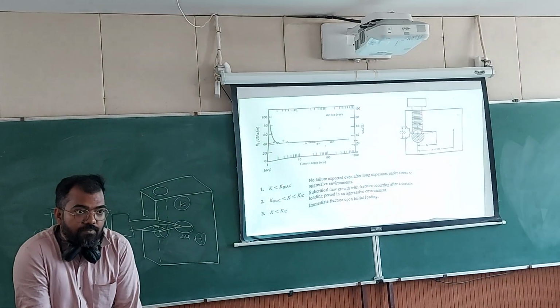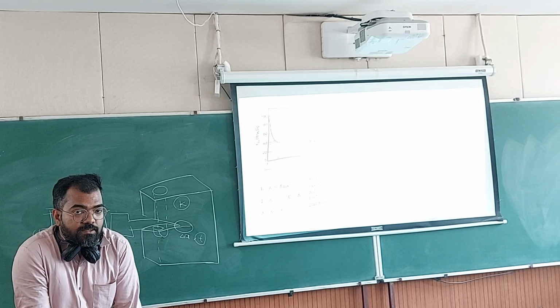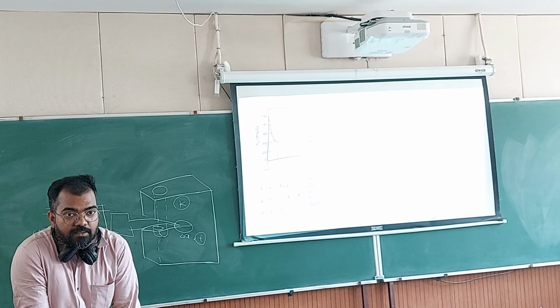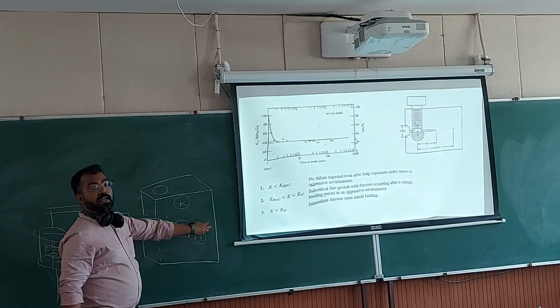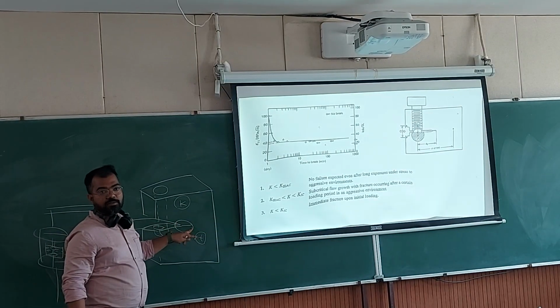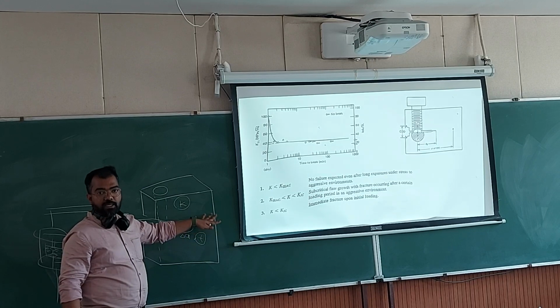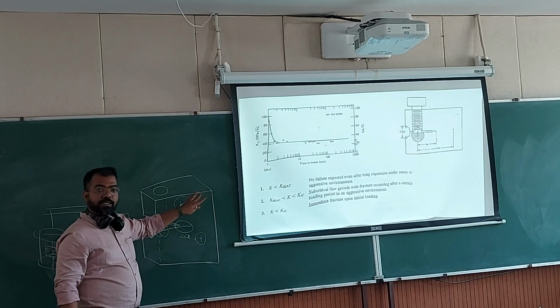Okay, similar things you can do in creep. You just put a screw in the sample, tighten it, and throw it in the furnace. Okay, and you will get the threshold. You can do it for different samples which are starting at different crack tip locations, and you can also see the effect of constraint, in plane constraint, and all those studies you can do.